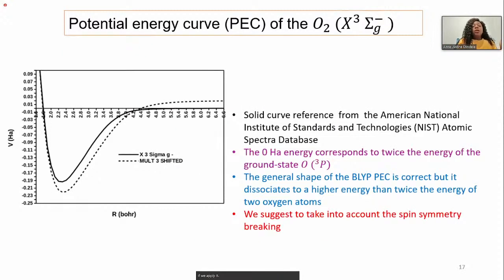If we apply it, we will find the potential energy curve of the oxygen molecule ground state, here in dashed line, that we compare to the experimental value from the American National Institute of Standards and Technology data. And we have shifted the potential energy curve by twice the energy of oxygen. And here it's done at the BLYP level. So we can realize that the dissociation of the two atoms is not correctly reproduced here.